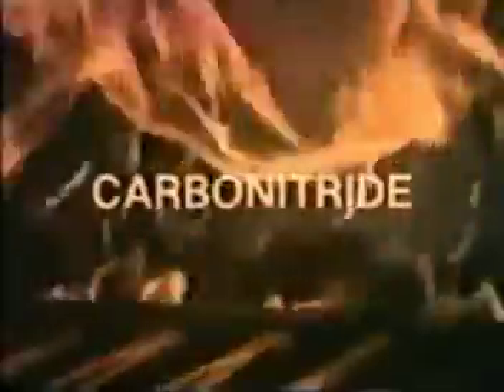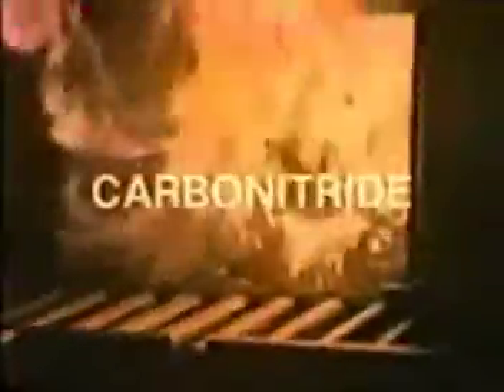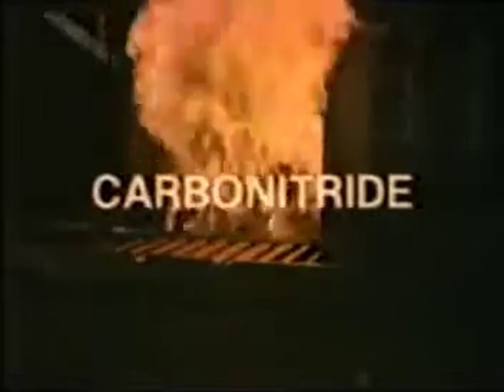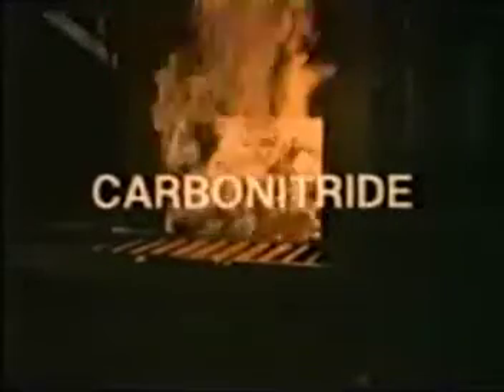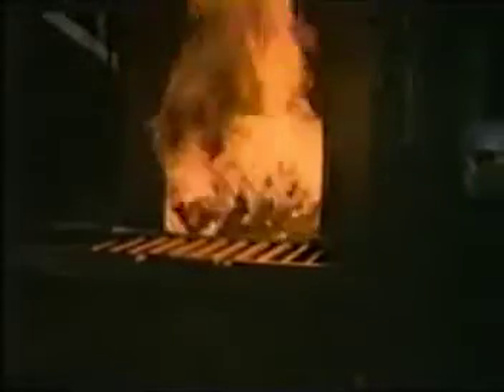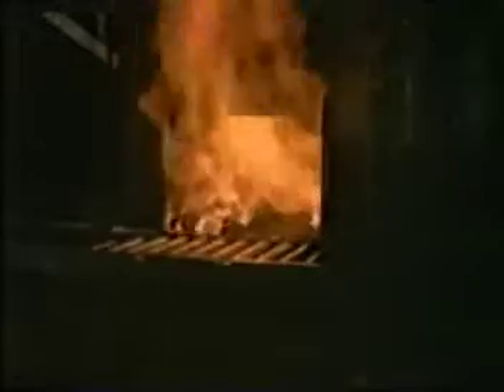Carbonitriding is a process in which carbon and nitrogen are added to the surface of steel from a gas atmosphere rich in both elements. Carbonitriding normally is used for case depths up to 20,000ths of an inch and is usually performed at temperatures between 1450 degrees Fahrenheit and 1550 degrees Fahrenheit.